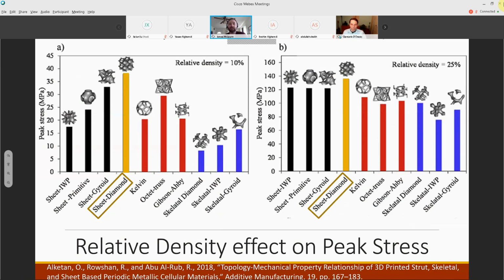So we looked at the data that we were given. We get a comparison graph here of the peak stress for relative densities of each of the different structures that they tested. We can see here we've highlighted the sheet diamond at a relative density of 10%. It's head and shoulders over the other structures, and then at 25%, it's not quite as greatly over the other structures, but it's still significantly better.